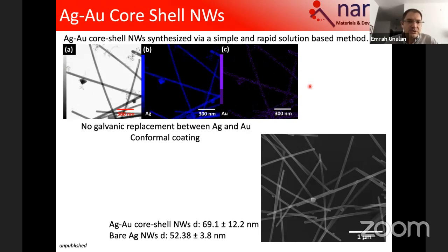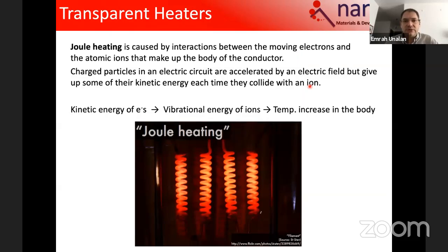Not going to spend so much time, but the scenario with the gold is the same. Again, with the solution methods, you can coat very thin layers of gold on top of silver nanowires to improve the electrochemical stability. I know platinum and gold are expensive, but trust me, we are putting a very thin 5 to 10 nanometers of gold and platinum, which is not increasing the cost so drastically. So let me move on with another device.